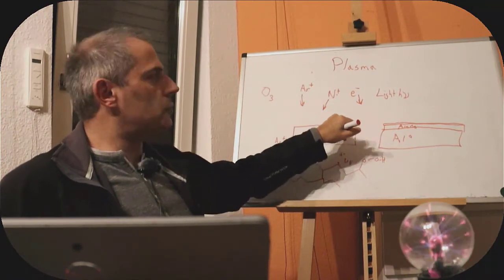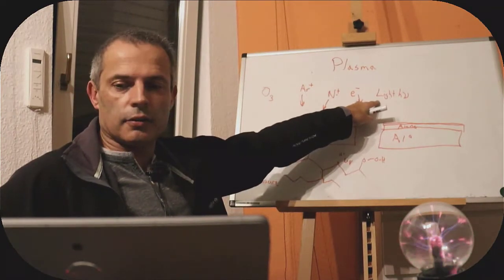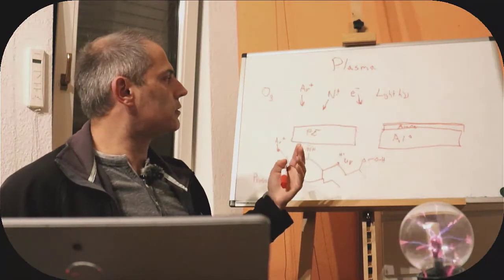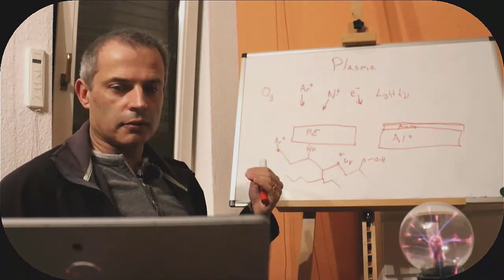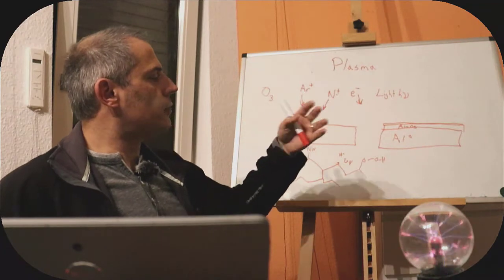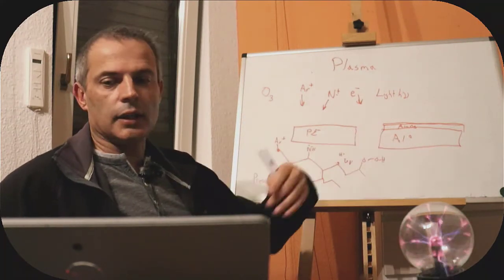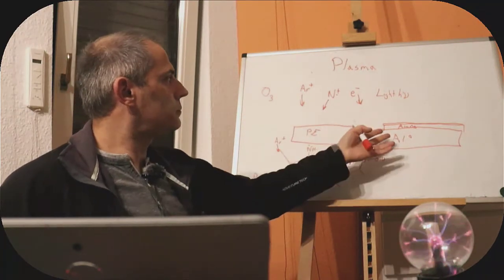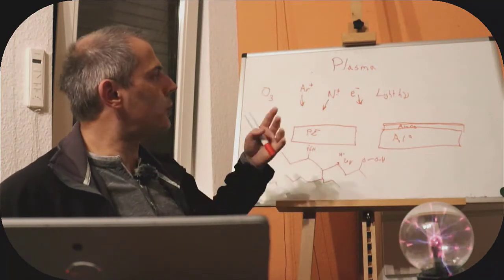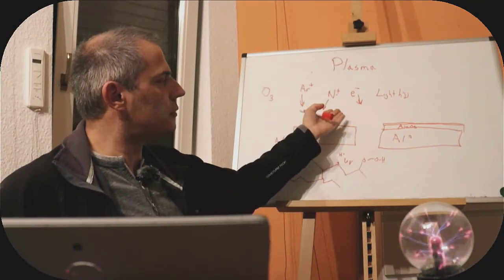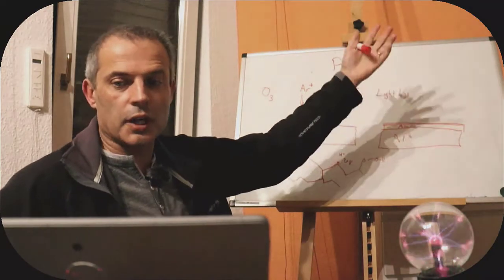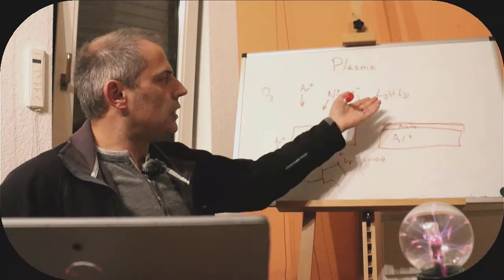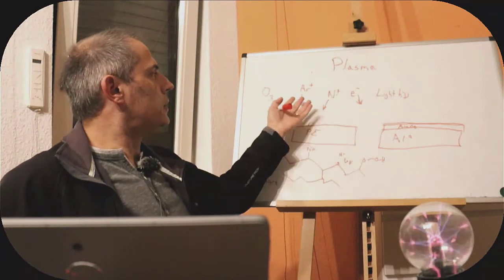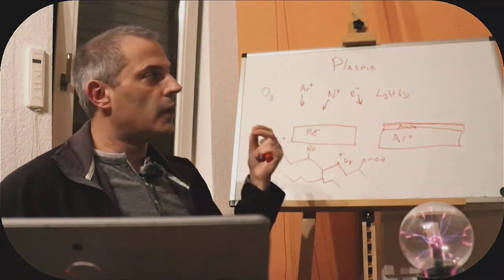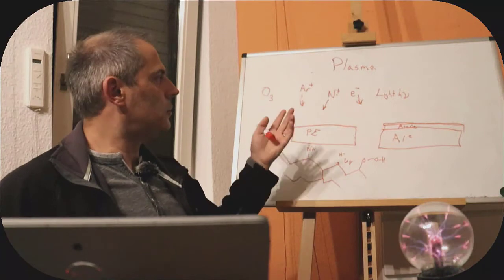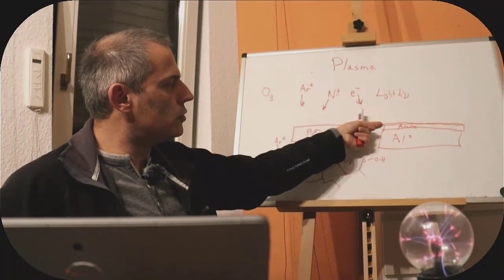If we want to make sure that we don't have ultraviolet light damage, we will have to think of a way to keep the amount of ultraviolet down. If we want to clean our aluminium oxide surface, we will have to think of a way of keeping the energy of the ions down so that we don't knock too much out, because the light is not going to do anything, but the argon ions, for example, if we give them the right conditions, they can remove all of our material.